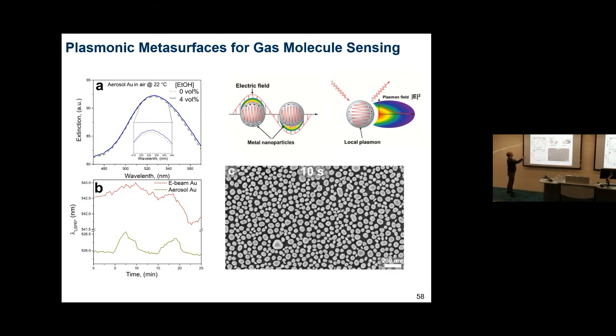So when you do that, for example, this is our nano islands that you see here, and we put 4% of ethanol, we see a very, very small, almost nothing shift, right? And if you use another method like beam evaporation of gold, similar or maybe a bit worse.